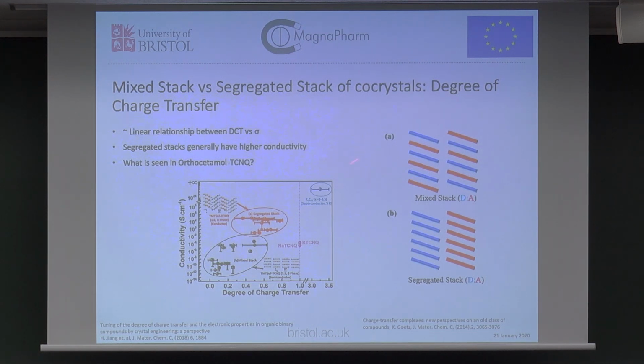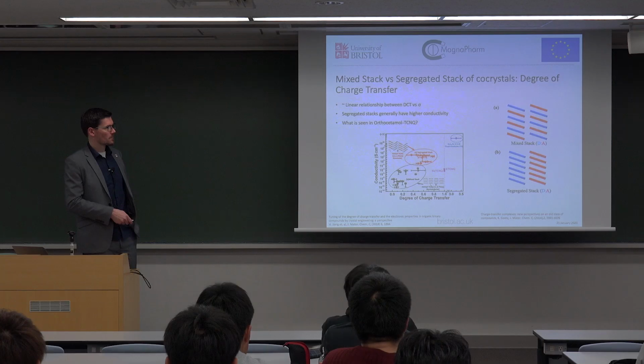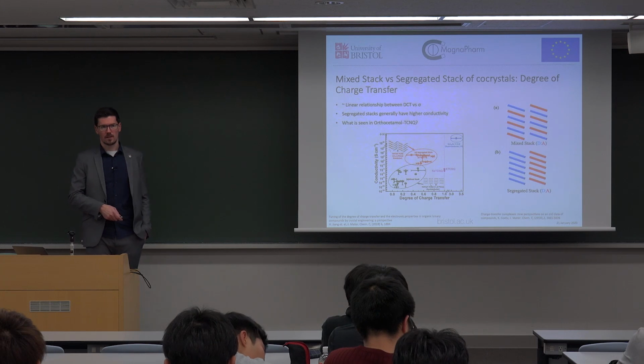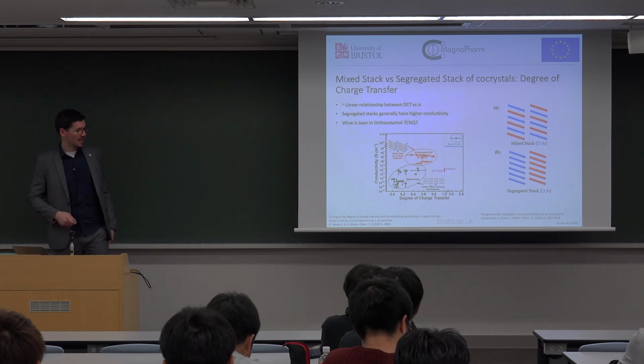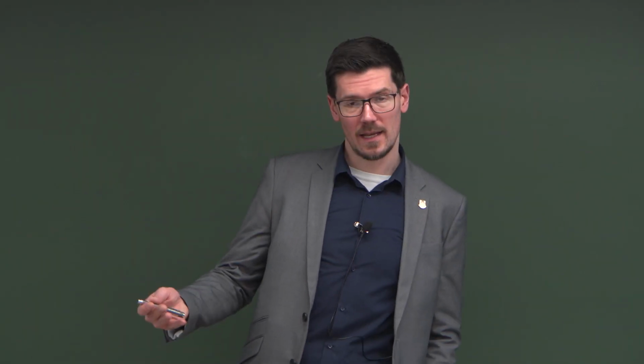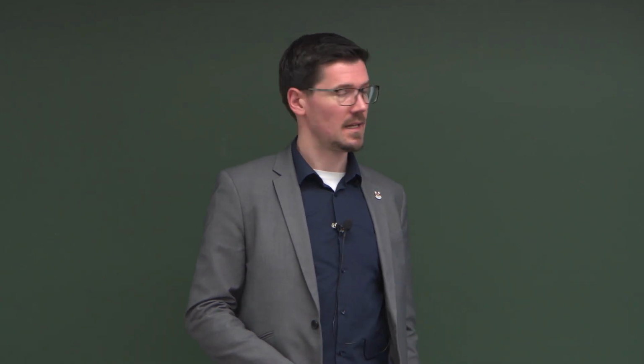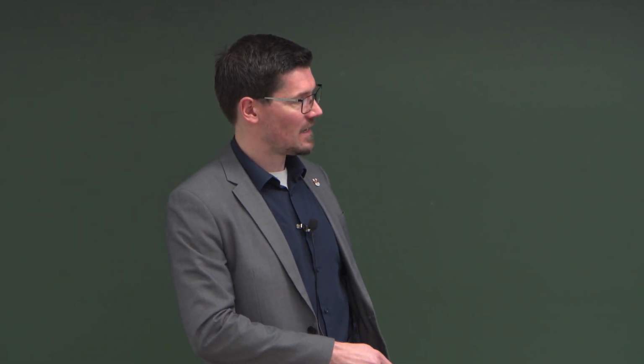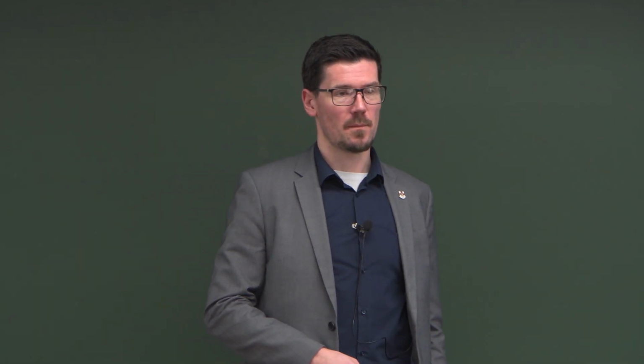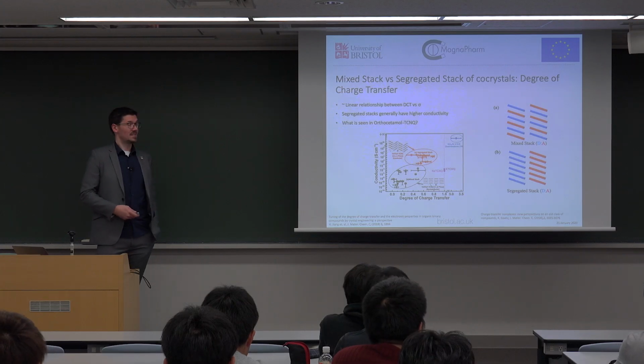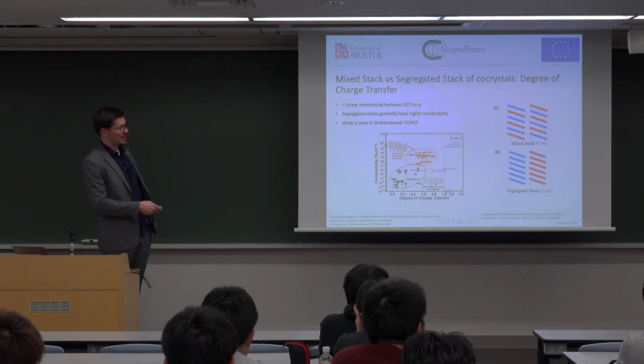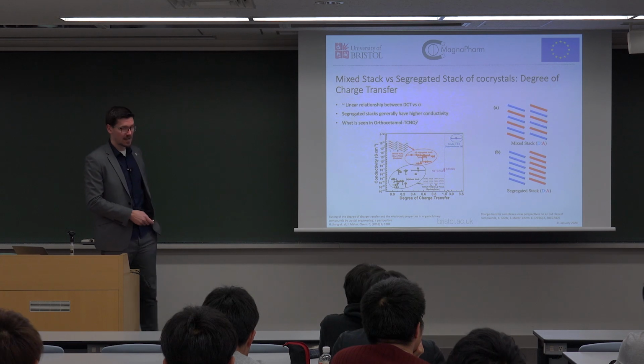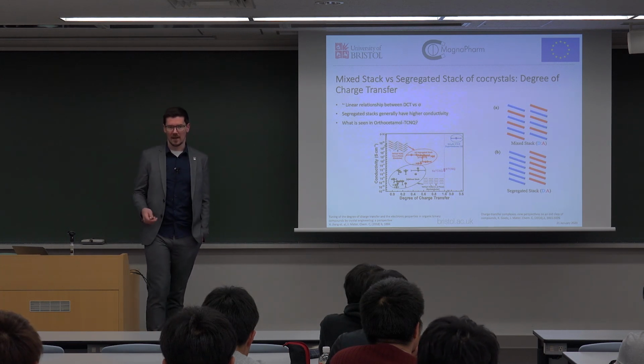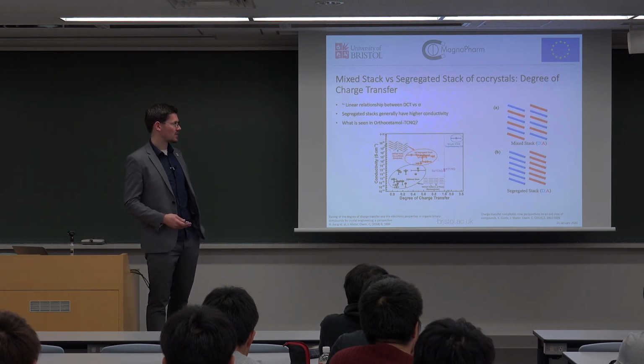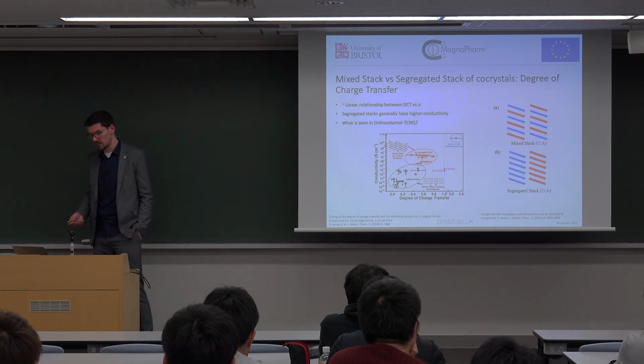So a mixed stack, which basically has alternating molecules in each stack, has typically a lower conductivity than the segregated stack, donor and acceptor. So if we can take something that grows in a mixed stack and make it a segregated stack, possibly using magnetic fields, then we can increase the charge transfer properties of these crystals.